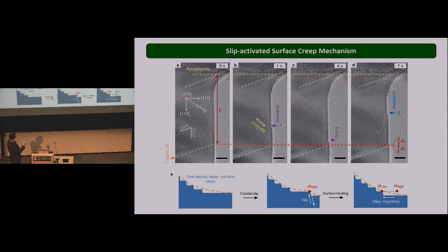And in this case, we show that it is actually the crystal slip that comes first, and that will activate surface creep. All right? So there's a dislocation here that nucleated and formed a step, and then that step in the next sequence moves and diffuses on the atomic scale. In this case, there's another step here that forms. So we came up with a model that explained this observation.